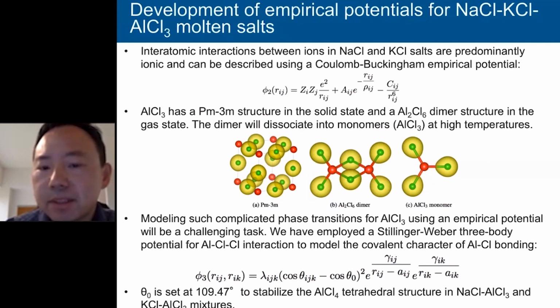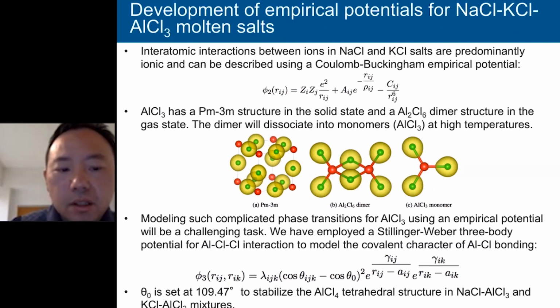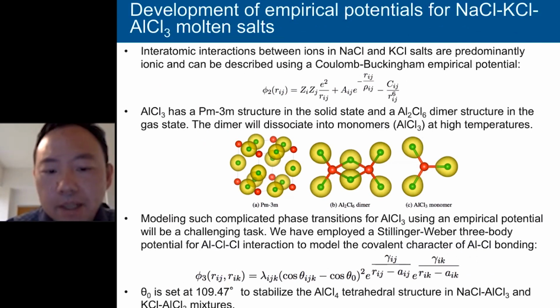And at even high temperature, the dimer will also dissociate into monomers. As shown in the right figure, each aluminum is surrounded by 3 chlorine, and the angle between them is actually 120 degrees. So modeling this kind of highly complicated phase transition using an empirical potential is a very challenging task. In this work, we have used a Stillinger-Weber 3-body potential to stabilize the aluminum chloride 4 tetrahedral